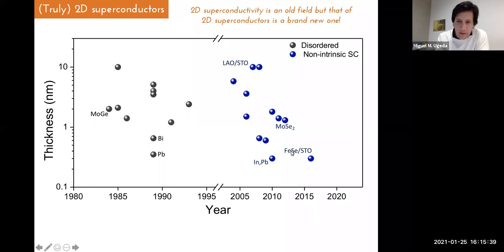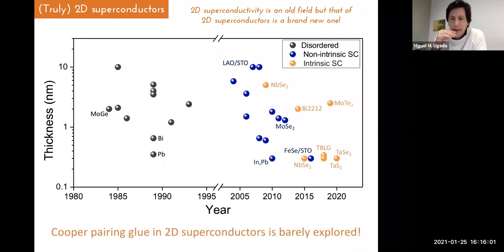Iron selenide becomes superconducting in a single layer form, but has to be attached or grown onto an STO substrate, or this is an interface between those 2D materials, and then at the interface, superconductivity develops. However, in the last 5 years, we have been witness to the emergence of truly two-dimensional superconductors, that are superconductors without the need of any substrate or any device attached to it. That's the case of, for example, niobium diselenide in monolayer form, other TMDs, even monolayers of cuprates, and the remarkable case of twisted bilayer graphene.